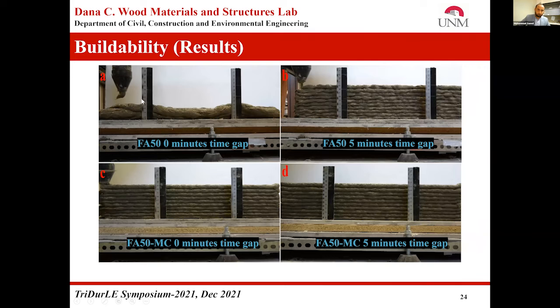To evaluate the buildability, we consider two time gaps between the printing layers, 0 minutes and 5 minutes. So the printing time gap means we printed one filament and then we waited for 5 minutes, and the second filament was printed after 5 minutes.